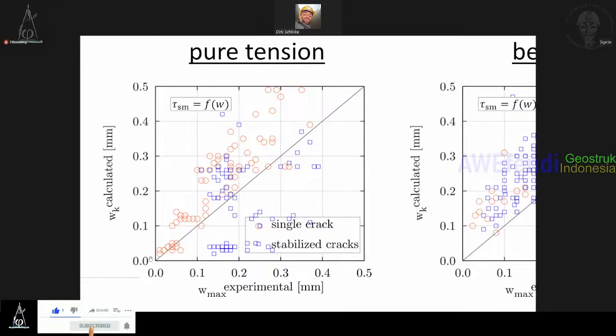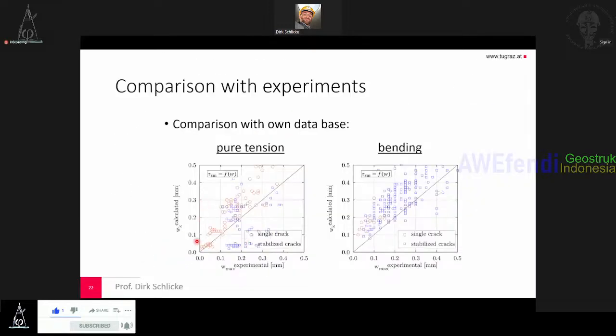And as soon as you come to the stabilized crack, there is sort of, I would say, confusion in the results. We still have it here in the result. Maybe I should remove these experimental data, because the definition of effective concrete area, which enters the calculation, is not very clear in the case of these experiments. So this type of experiment is not really representative for what happens in reality, let's say.